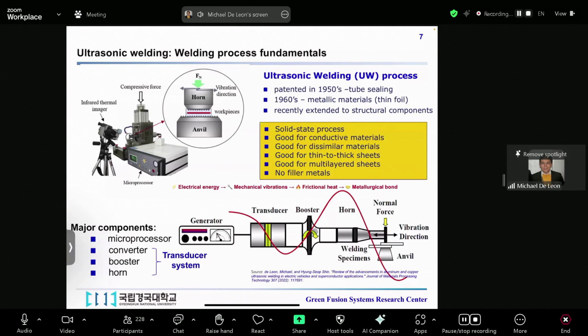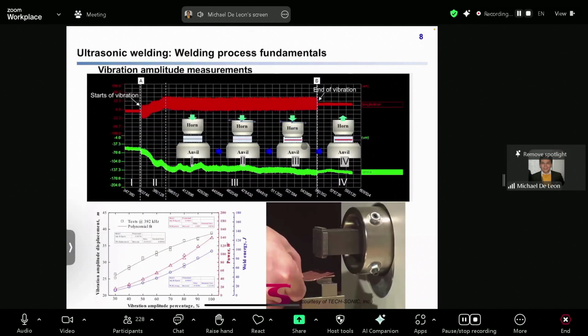The horn delivers ultrasonic vibrations with enough energy input to increase the weld zone temperature and achieve plasticization, which results in softening and simultaneous joining. After the determined welding time, the horn retracts and allows the welded workpieces to be removed from the anvil.